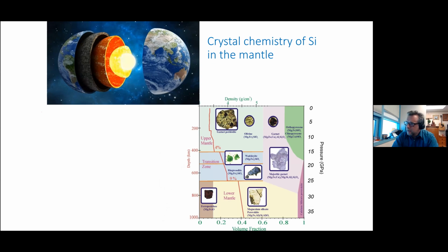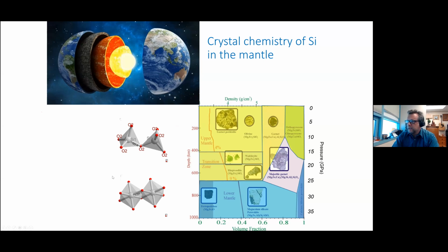So this is a figure that I took from Dan Frost's paper that shows the major mineral phases present at different depths in the earth. And you can see that at shallower depths, the surface is at the top of the picture, and we are going deeper and deeper towards the bottom. We have phases with tetrahedral coordination, like these tetrahedra from quartz. And then at certain depth, we are getting to the regime where octahedral coordination is more preferred.